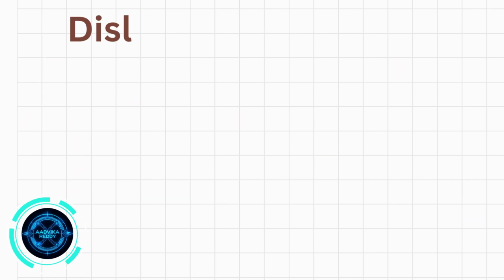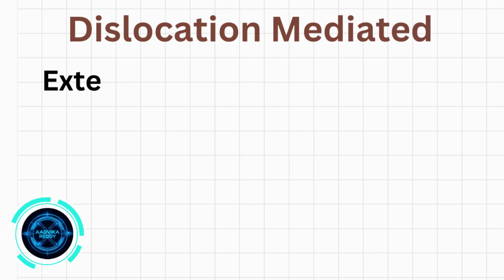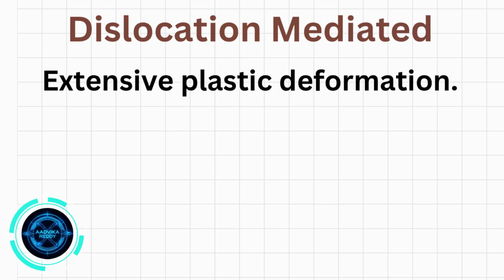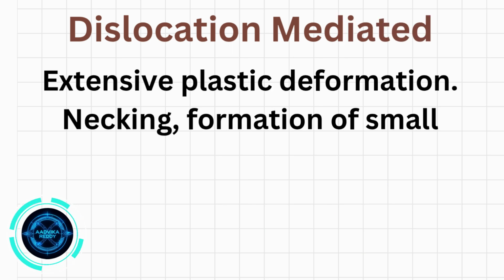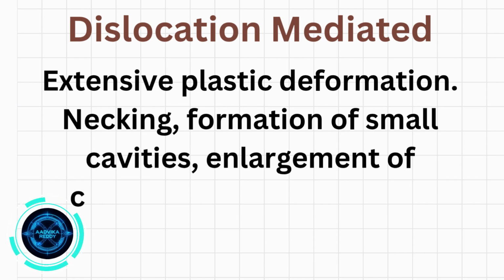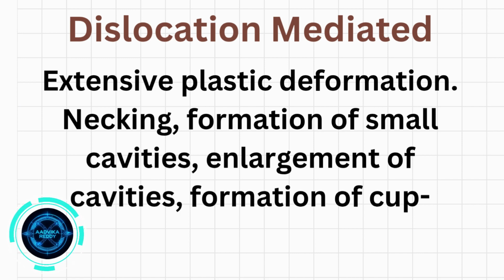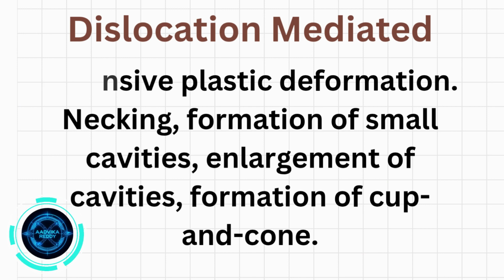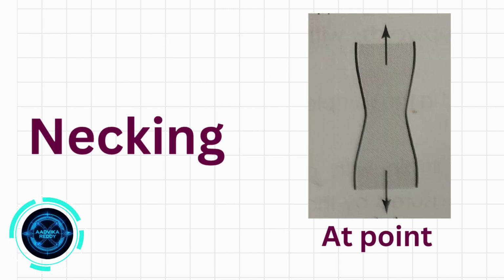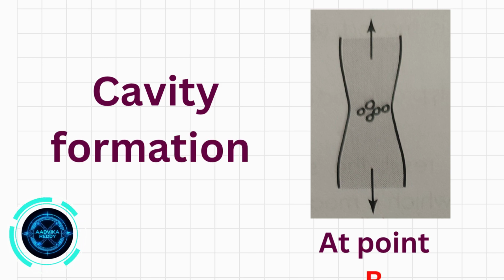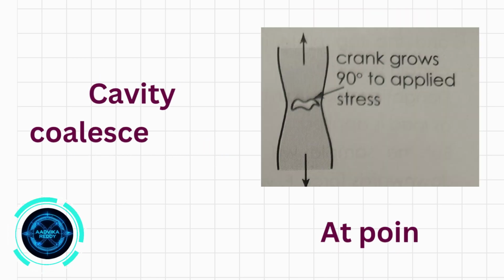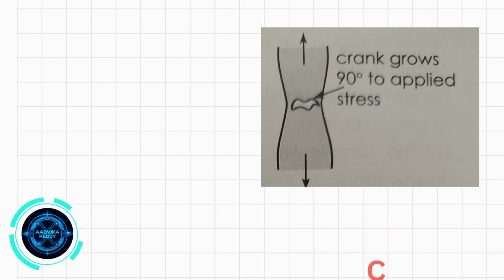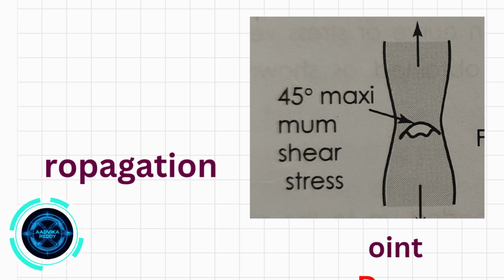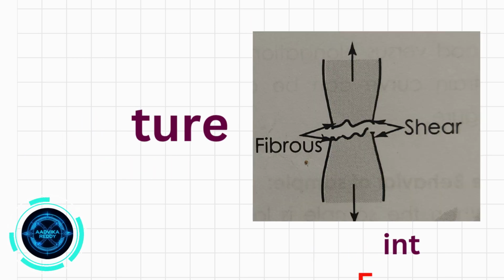Failure behavior of sample: ductile fracture, dislocation mediated, extensive plastic deformation, necking, formation of small cavities, enlargement of cavities, formation of cup and cone. Typical fracture structure with dimples: A. Necking, B. Cavity formation, C. Cavity coalescence to form a crack, D. Crack propagation, E. Fracture.